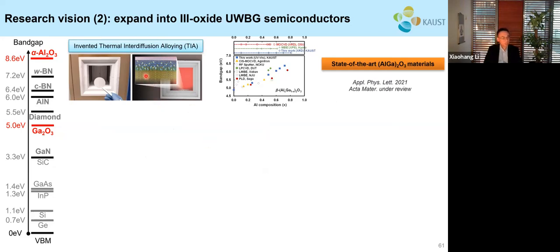So one of the studies is that we have invented a new technique to grow ultra wide bandgap semiconductor. We call it thermal interdiffusion alloy. So in this process, we did not need any precursor or more complex equipment such as MOCVD, MBE, or PLD. We just need a simple thermal furnace, which costs just a few thousand dollars. And we just have to put a gallium oxide layer on top of sapphire into this furnace. And with annealing, we can form aluminum gallium oxide with different composition, different thickness, and different material quality for device applications.